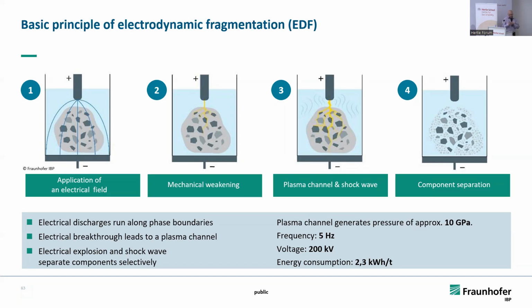This is spreading very rapidly. It generates a pressure of up to 10 gigapascal, which is in the range of a TNT explosion. And then you can tear apart the concrete. And this is the only technique which only has to overcome the tensile strength and not the compressive strength. And the good news is